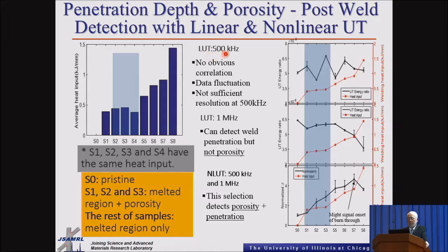When we used linear ultrasonic testing using 500 kilohertz, you can see there was no correlation between the changes in heat input and the UT signal. The same thing here, and remember that in here the heat input is the same. The only difference is that we have changed the porosity, so we have increased the amount of oxygen. We increased the frequency to 1 megahertz, and again you can see there was some decrease in the energy ratio, because we have more attenuation of the wave, and you can see the drop in here. So in a sense, when we go to higher frequencies, it is possible to detect some changes in the penetration. However, any changes in the case of porosity could not be detected.